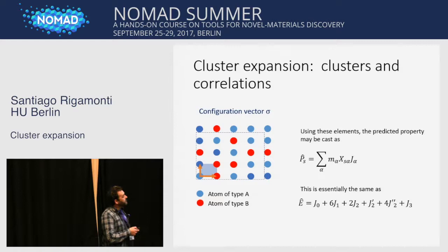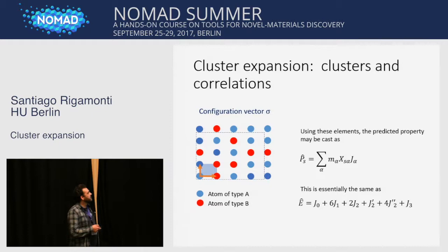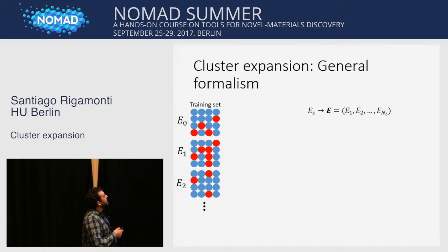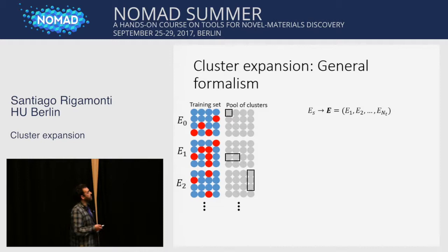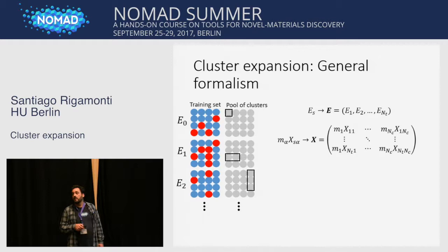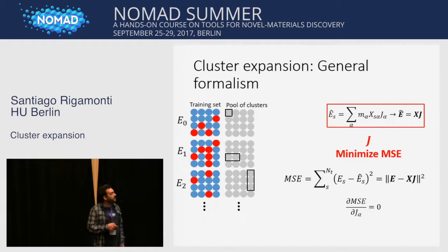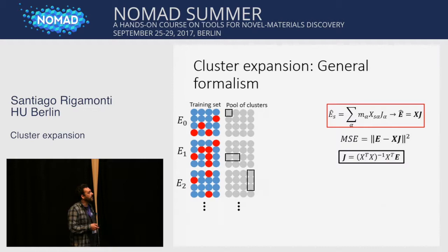These numbers are the product of the multiplicity by the cluster correlations. What we do for the structures is to have a training set of arbitrary structures. With this training set we build a vector of energies. Then we have a pool of clusters, and we build the correlation matrix where every column is a cluster and every row is a sample from the training set. We then write the predicted energy as before, and must find the cluster interactions. We minimize, in principle, the mean squared error — this is the easiest way, and there is an analytical solution written in terms of the correlation matrix.